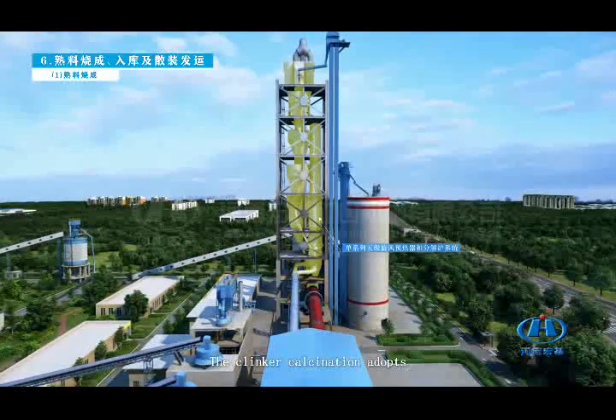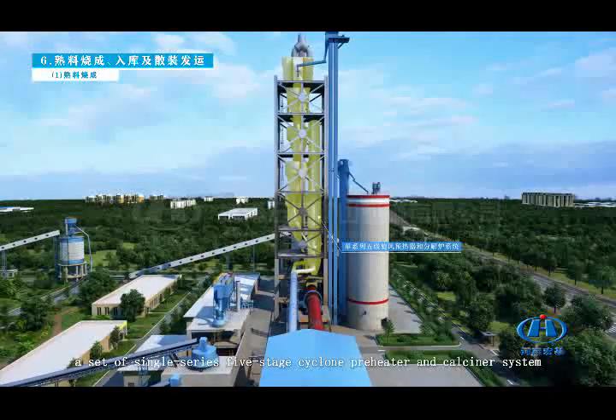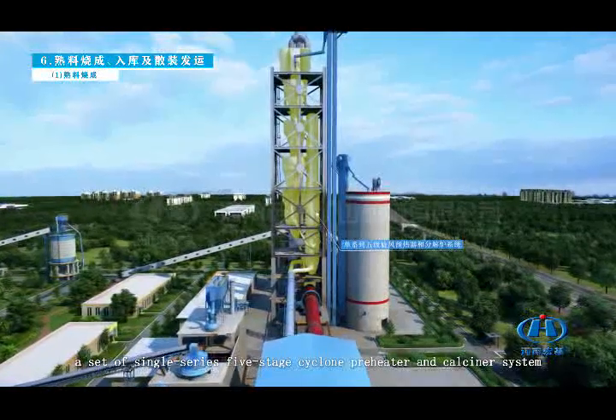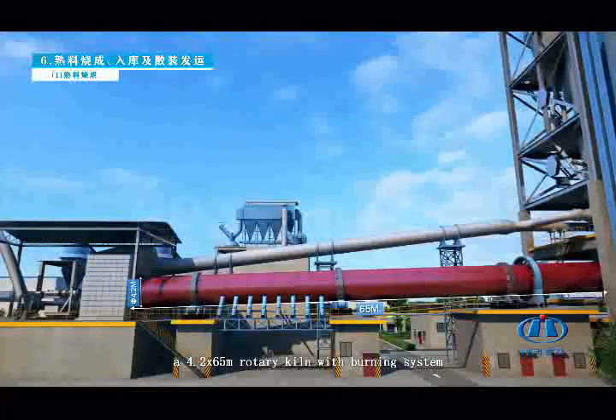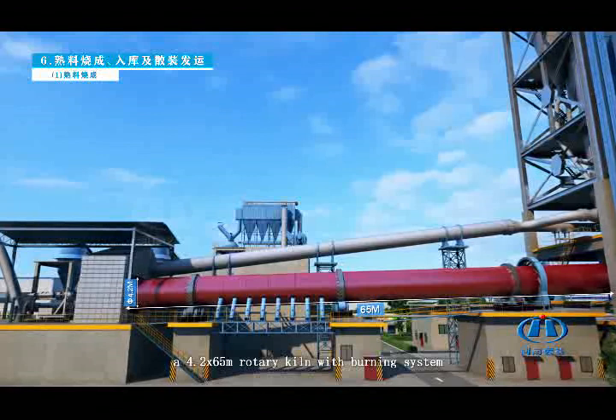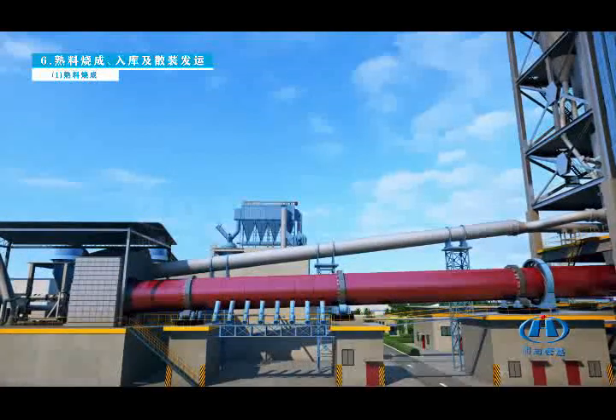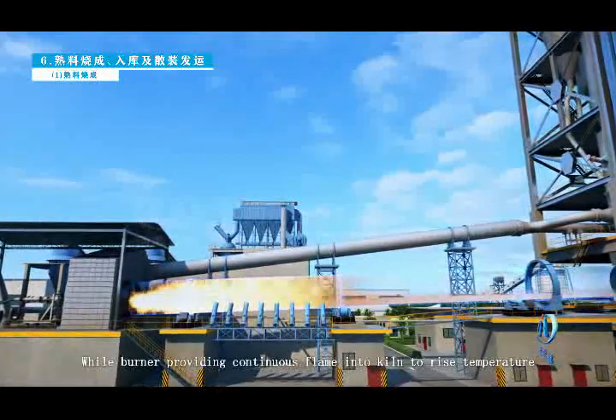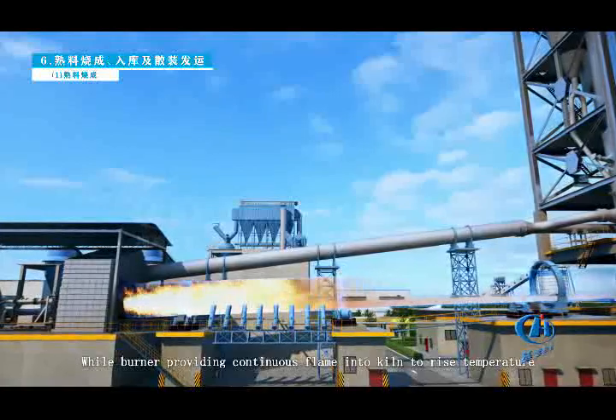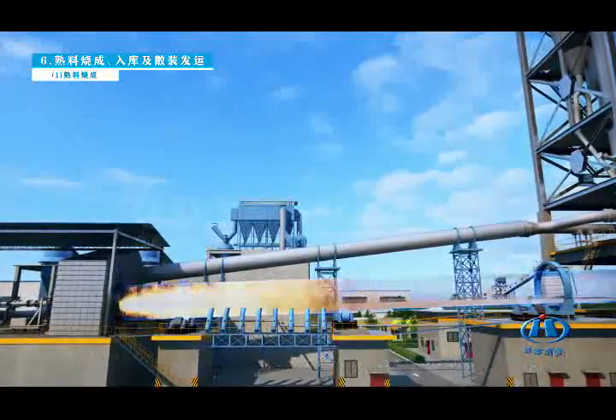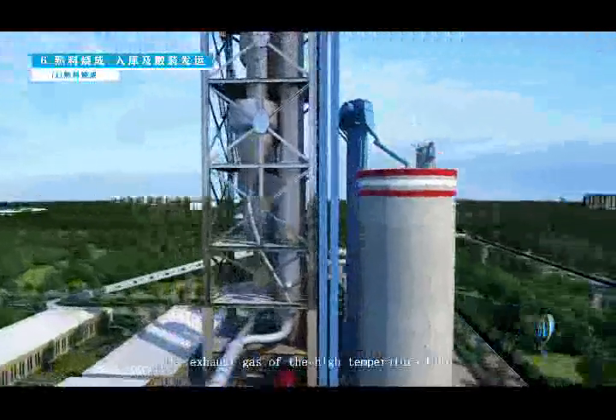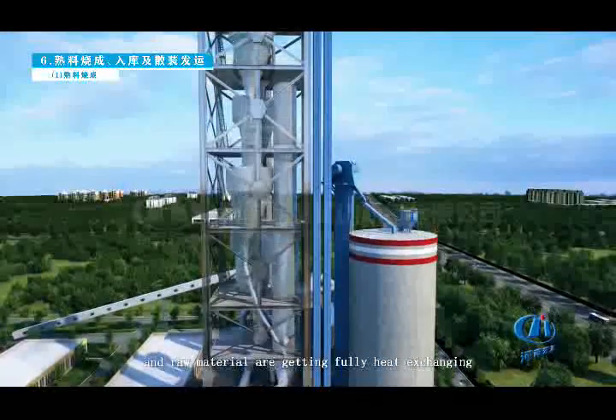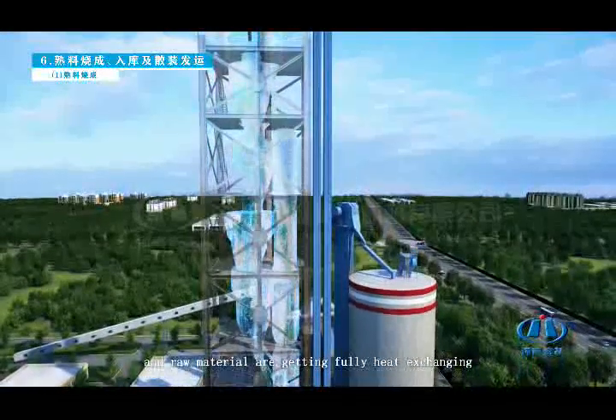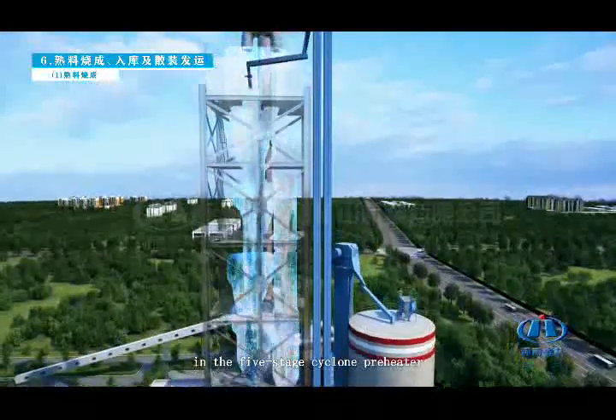The clinker calcination adopts a set of single-series 5-stage cyclone preheater and calciner system with a 4.2 by 65 meter rotary kiln with burning system, while the burner provides continuous flame into the kiln to raise the temperature. The exhaust gas of the high-temperature kiln and the raw material are fully heat exchanging in the 5-stage cyclone preheater.